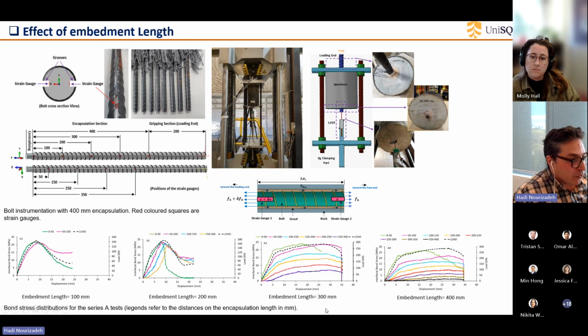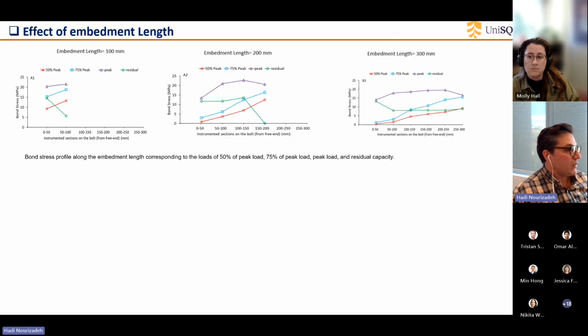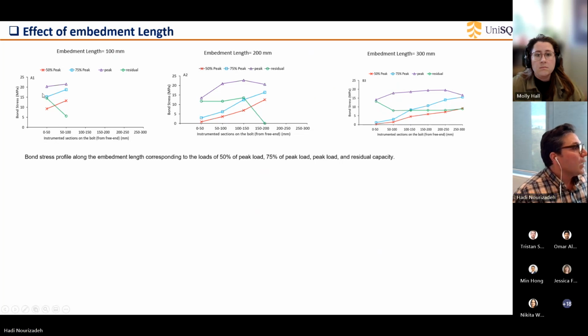But interestingly, for 300 and 400, as you see here, when the displacement of the bolt reaches around 20 to 50 millimeter, we see the debonding here. But after that, we don't see any debonding till reaching the ultimate bearing capacity. So it is very important in terms of designing our materials. Also here we have some diagrams showing the embedment length and the bond stress, considering the different levels of pullout.